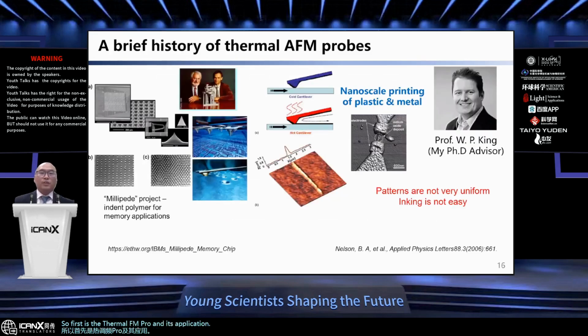So this is a brief history of thermal AFM probes. As I already mentioned, Dr. G. Binnig invented STM and also AFM. Then IBM invested in this big project called Millipede. Basically, this project employs 32 by 32 thermal probes that can be individually addressed to heat up. Then you can imagine about 1,000 AFM thermal probes can indent a polymer substrate to achieve a high-density storage function. But unluckily, this technology was not commercially successful. But it has had a lot of success in other fields.